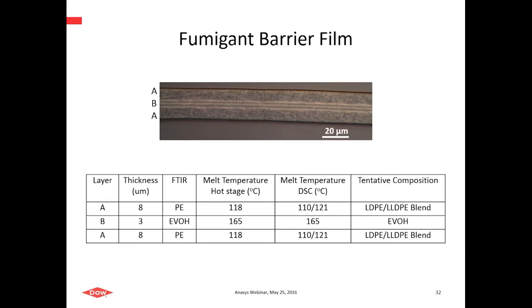So this is an example of a commercial fumigant film shown in cross-section at the top using optical microscopy. Again, the total thickness is about 20 microns. And the conventional methods we would typically use to characterize these kinds of films would be FTIR or ATR on either side, and then FTIR through the entire film multi-layer stack.